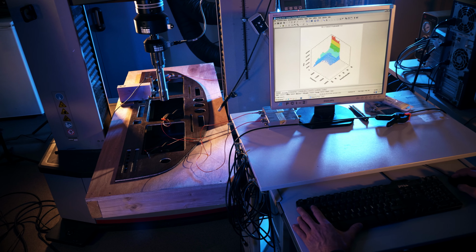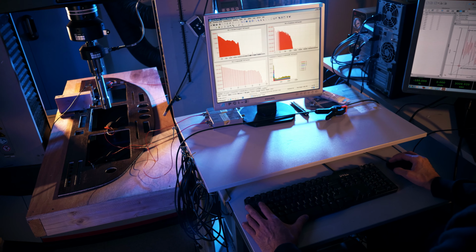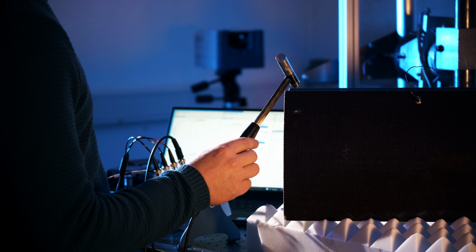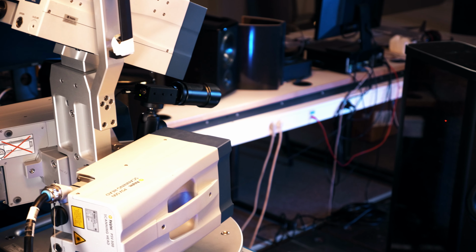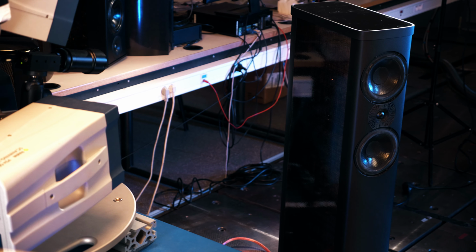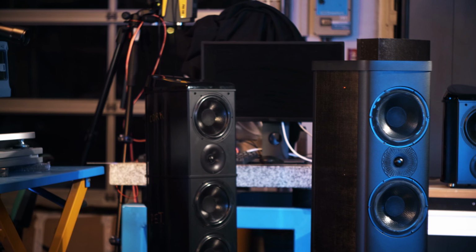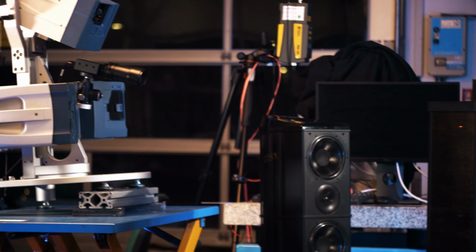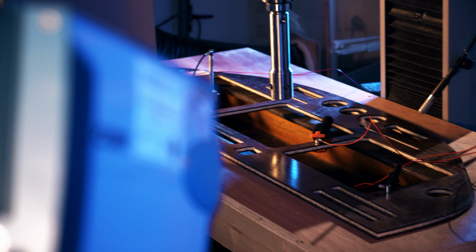Sensitivity to moisture is specific to plant fibers compared to traditional glass and carbon fibers. Damping capacity is another one. The use of plant fibers' damping capacity within a composite is still not sufficiently valorized in vibroacoustic control to mitigate resonance. So, at SSUCHY, we also put an emphasis on the damping behavior of lightweight bio-based composite and sandwich materials for applications in the transportation and acoustic sectors.